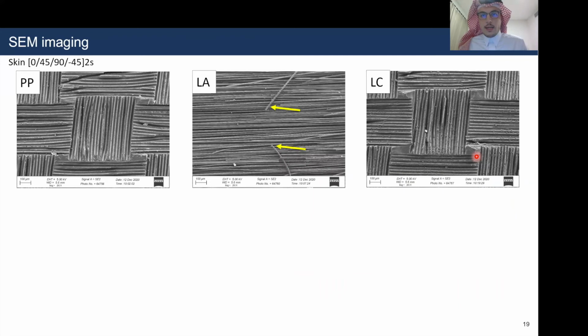So the SEM images were taken at the interface of each pretreatment. The purpose of this imaging is again to illustrate the effect of the pretreatment technique, and this is before the failure, as I highlighted earlier. So we can see here the peel ply pretreatment, and we can see some particles on the surface. Similarly, in the LC, we can see the same particles or very small exposure, if any, of the fibers. However, in the LA case, we can see the fibers fully naked and fully exposed.